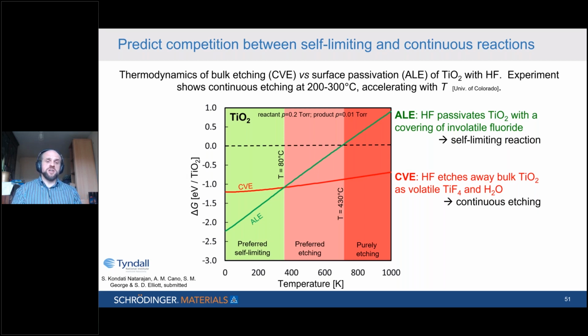The other possibility is the HF hits the surface and passivates it and covers it with a layer of involatile titanium fluoride. And that then stops any further etching taking place. And this would be the condition for atomic layer etching, where you have a layer by layer process. You would passivate the surface with HF and then bring in a second reagent to remove that fluoride layer, generate a bare surface again, and go again with the HF. So that would be a layer by layer, very controlled way of etching. Now, which one is going to take place for any particular material, that's not entirely clear.